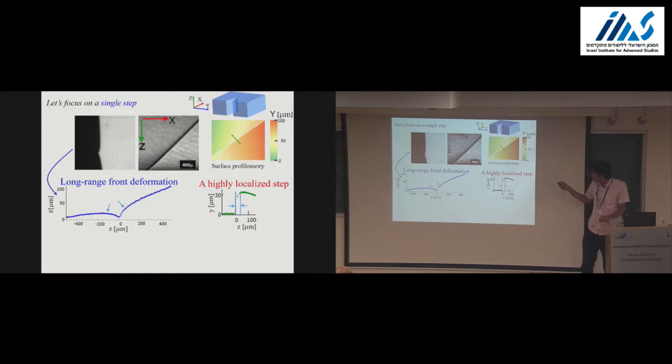And we see that if we take a cross-section along the step, the step is highly localized, on the order of 30 to 50 microns. So what is the origin of this deformation?